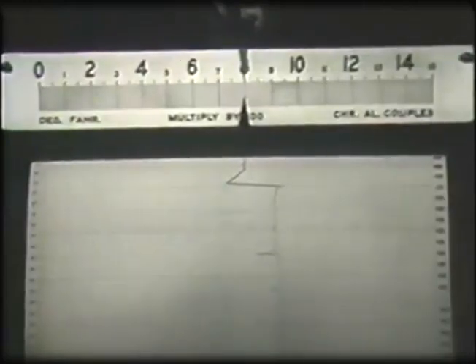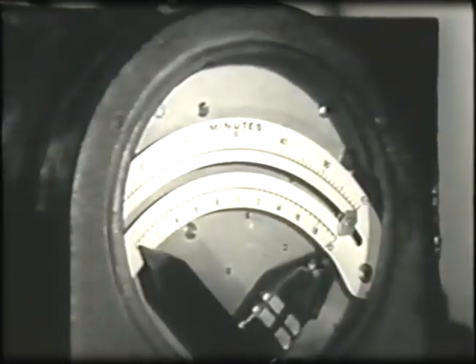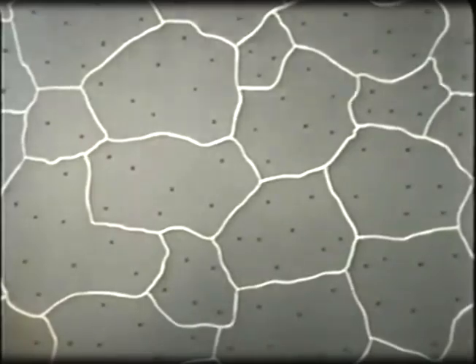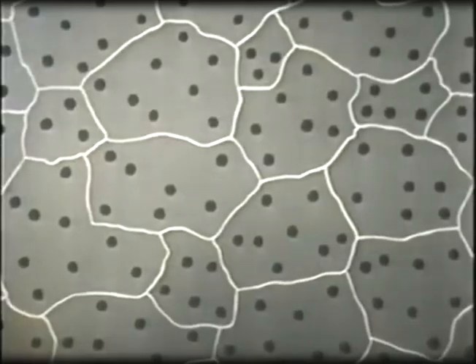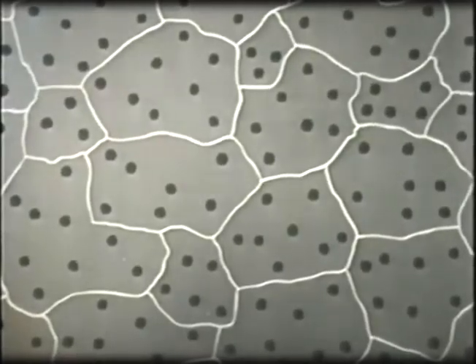Full annealing to remove the effects of both cold working and heat treatment, or of heat treatment alone, is accomplished by heating at approximately 800 degrees Fahrenheit for from 1 to 2 hours. The alloy parts are then allowed to cool slowly in the furnace. Once more, the first internal change is that of recrystallization, removing the effects of any cold working that may have been present. But this time, in the second change, most of the CuAl2 is precipitated out of solution in the form of coarse particles. The metal is now in the annealed or soft condition.